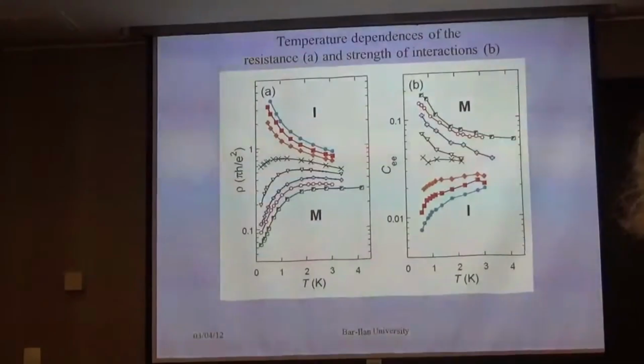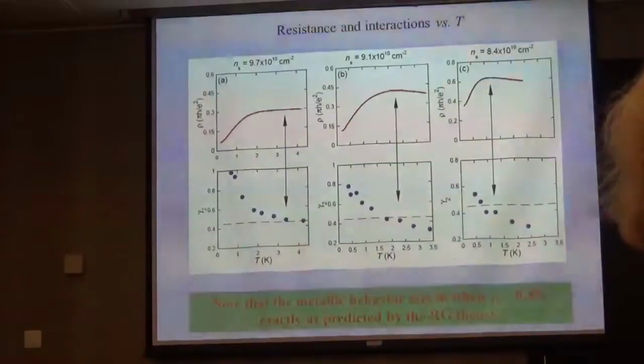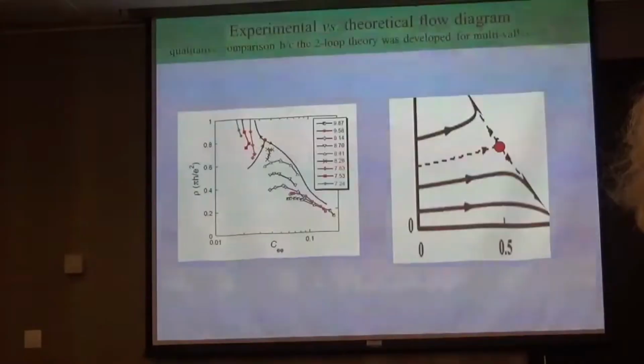So we were trying to verify this phase diagram, whether it works or not. We measured resistance as a function of temperature and also strength of interactions as a function of temperature. It's not really Coulomb interactions, it's spin-related interactions. And it turns out that both of them depend on temperature. So we have disorder and we have interactions, and we can plot them on the phase diagram. I just replot those data which I showed as disorder versus interaction. This is our experimental points. Those black lines are not experimental points, they're just guides to the eye.